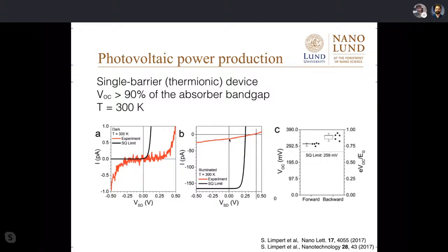We plotted in comparison the theoretical limit if this was a p-n junction. The theoretical limit for a normal single junction solar cell is the Shockley-Queisser limit. And it turns out two things here. We get much less current than one would, in the ideal case, hope for. The system is not at all optimized. So this is a comparison. We have only about 10% or less of the current than one could hope for. But we have a higher open circuit voltage at first attempt. So we have an open circuit voltage that's higher than the thermodynamic limit for a normal p-n junction cell. This is this extra oomph we get from using a thermionic system here. So it's not a good solar cell, but it has at least the hallmark of something interesting happening here.